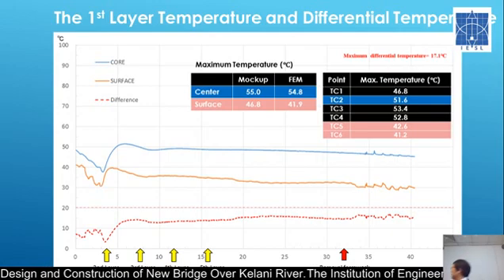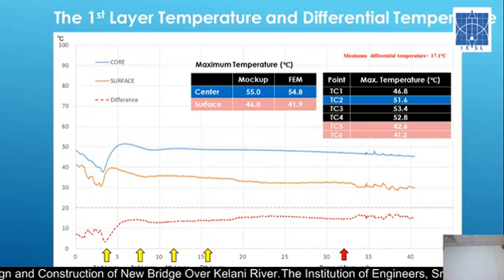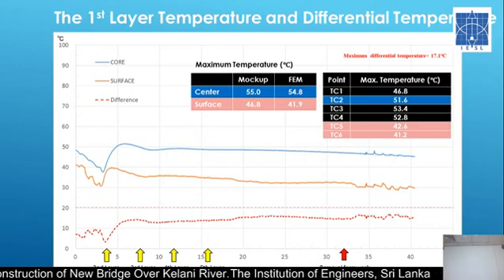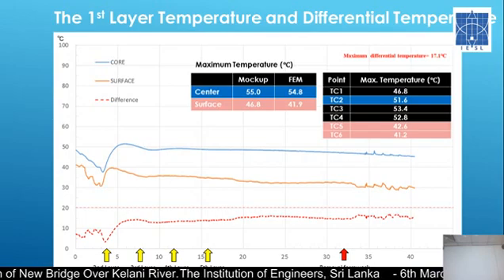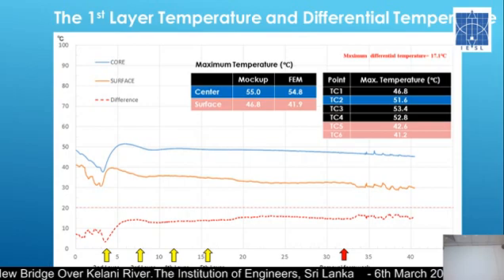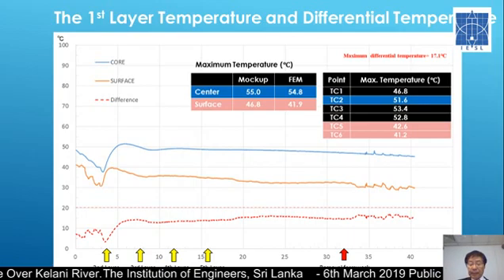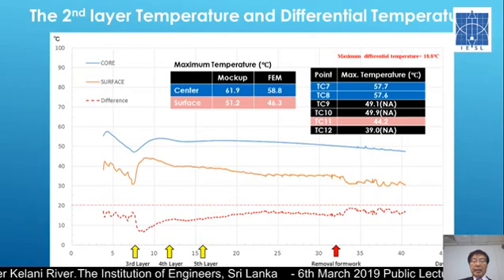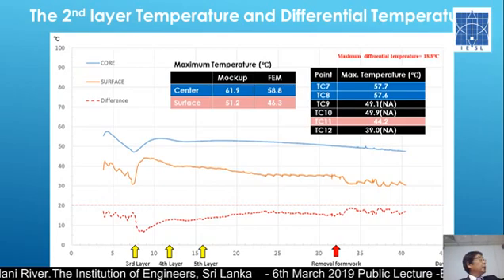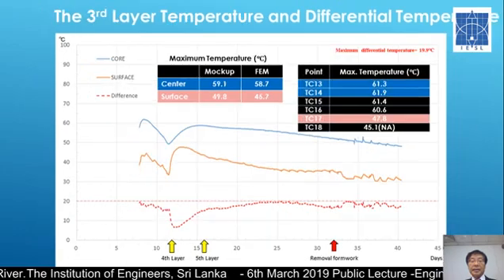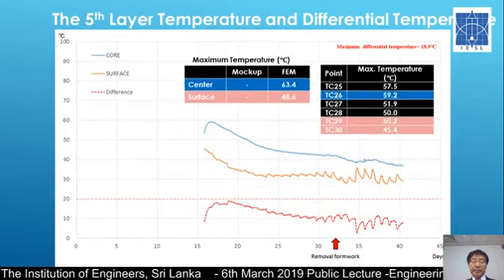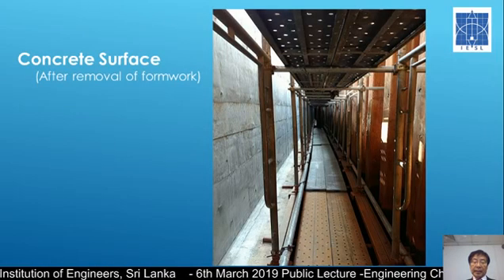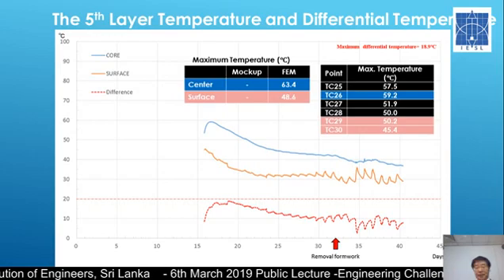So first, when the first concrete is cast, the temperature drops a few days later, and then when the second layer is cast, you see the temperature rises to this level. But for the third, it seems not much impacted. It's a very interesting curve, showing the accumulation of temperature from layer to layer. I will show the same for the second, third, fourth, and fifth layers, but because of time I would like to go quickly. If I explained it, this would take about 10 minutes.